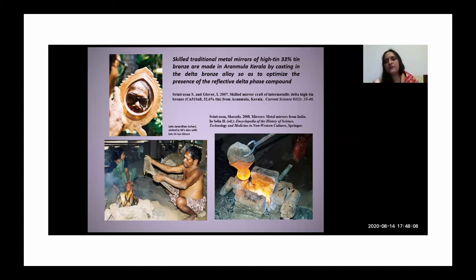So basically what they were doing is they were using what I would describe as a closed crucible cum mold process for casting, which is quite a mouthful, but I'll just explain that. So basically, you would create a crucible which can function both as a crucible and a mold, because in that cup, which you see pointing downwards, that's where the metal to be cast has been packed. And on the top of it, there's a set of two-piece molds with a gap within which the mirror blank would be cast. And so it's heated face down in this hearth and then tipped over, turned over the other side, so that then the metal flows into that gap. And I'll also show you how that's done.